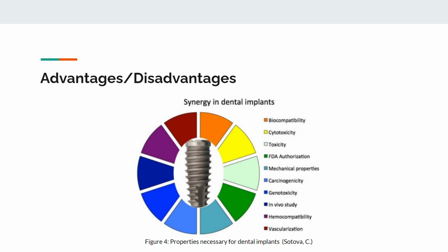Depending on amounts of additives, the properties shift slightly. It is very important for the pH balance to be maintained, as mineral loss is initiated at 6 to 6.8 pH in the root and 5.4 pH in the enamel. In order to increase the mechanical properties of the polymer matrix with inorganic filler particles, the silane coupling agent increases the chemical interfacial adhesion. Surface pretreatment is necessary to ensure durable bonding to the resin. Lastly, the initiator-accelerator system cures the composite by utilizing a chemical reaction or light.